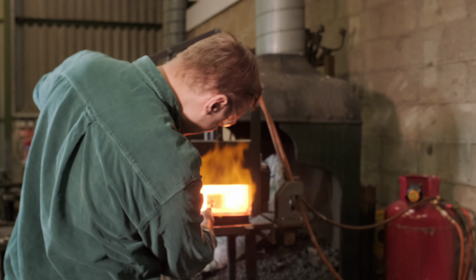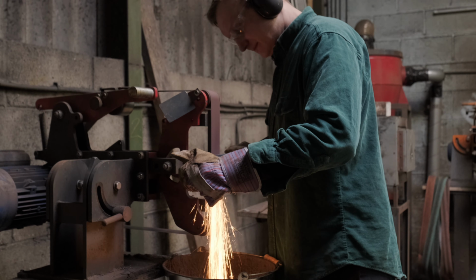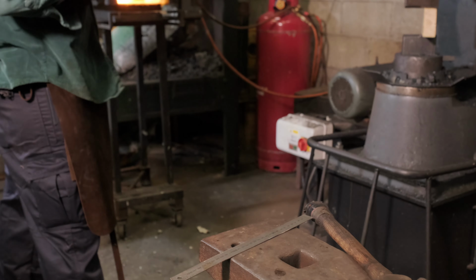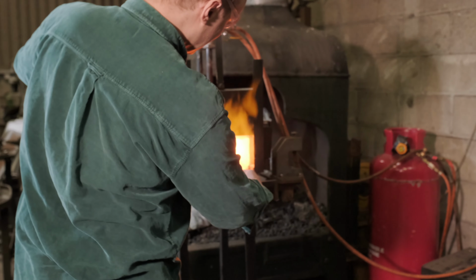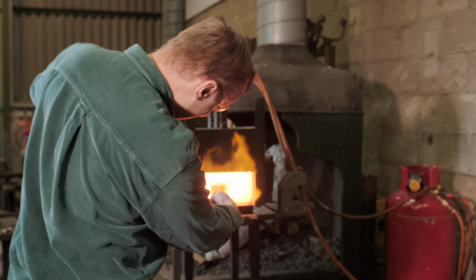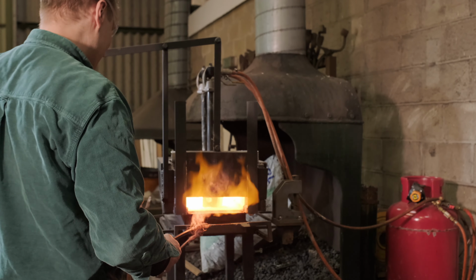I usually don't even use the borax if I've got a nice tight stack, because there shouldn't be any oxygen going in there. But this is like an extra layer of security for your stack, so you don't end up wasting all your work. Because the thing with cold shuts, you're not gonna notice them until you start grinding thin, so you're gonna do all the forging, and you might end up with a knife that you're gonna have to throw away, unfortunately. So now, we're gonna let it cook until the whole thing gets up to temperature.